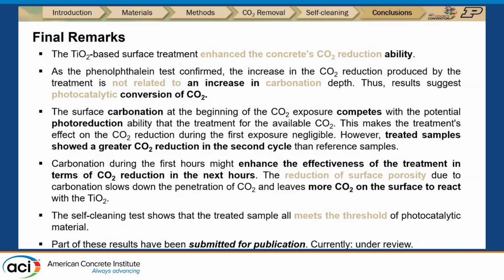This is because the porosity in the surface layer is reduced, letting the carbon dioxide stay on the surface layer and react with the titanium dioxide. The self-cleaning test tells us the treated samples all meet the threshold to be considered a photocatalytic material. Part of this work has been submitted for publication and is currently under review.